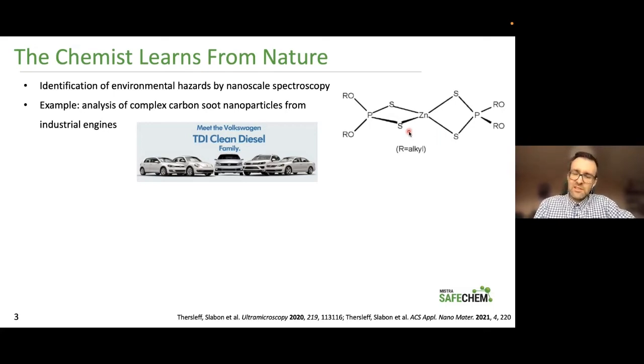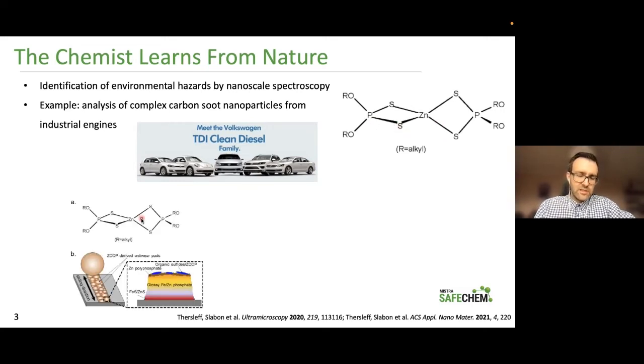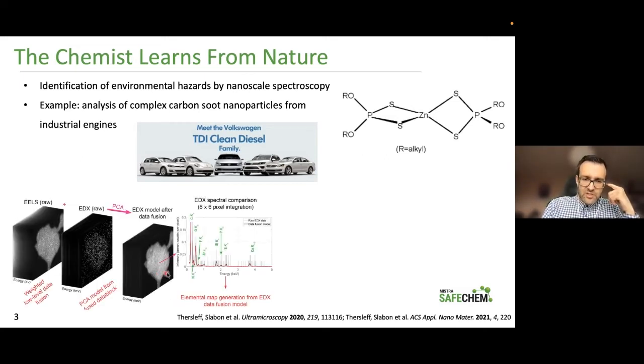But what's happening here in motor oils, you're giving this as an additive, and then it's believed that this chemical decomposes in situ. It makes a tribofilm on the surface, and it protects the surfaces and enables efficient lubrication. But if you think about green chemistry, you have to think about the full life cycle. So what's happening at the end of the performance of the product? And that's where we came in, because it was believed that these kind of, let's say, polymeric films, they decompose into safe end products in carbon soot particles. So this is a carbon soot particle which you get from motor oils at the end of the life cycle.